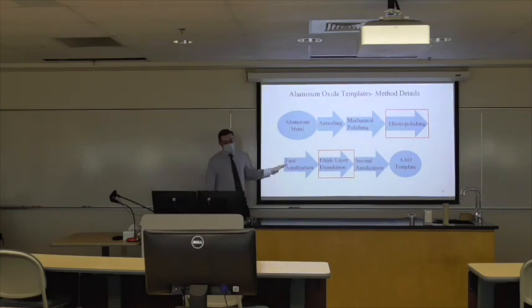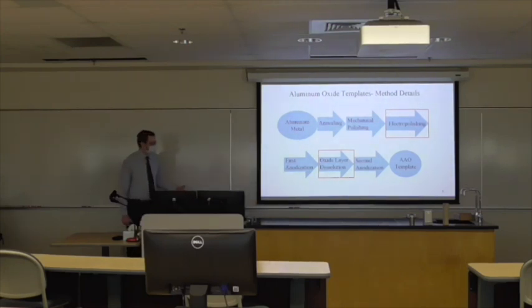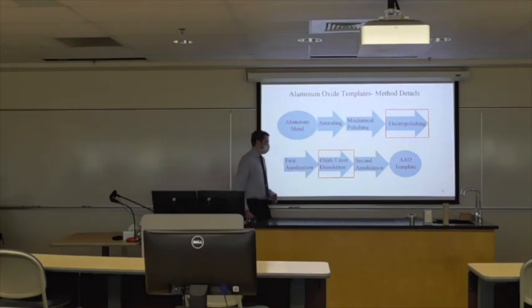Then the anodization step. So anodization is generally done using things like oxalic acid or sulfuric acid, phosphoric acid. Those are the electrolytes that we're going to use to make these. In Masuda and Fukuda's approach, they use oxalic acid, and that's a pretty common one to use. So that's generally the first step. Where we're doing a two-step anodization, then we have to dissolve the oxide layer.